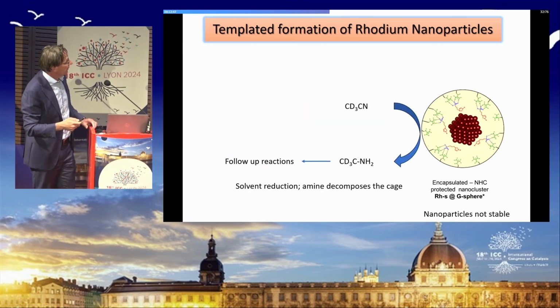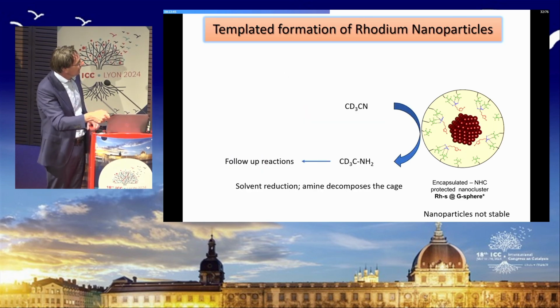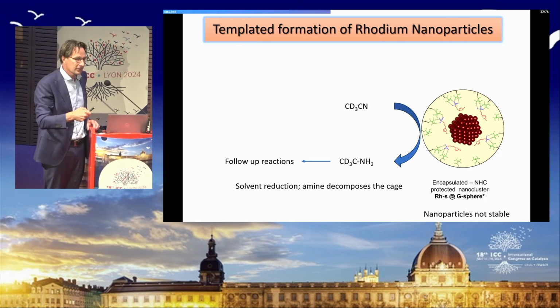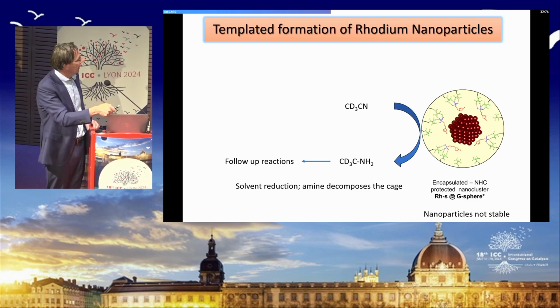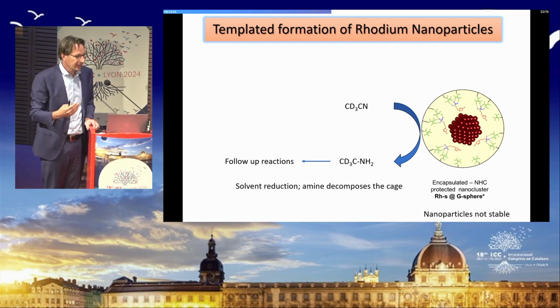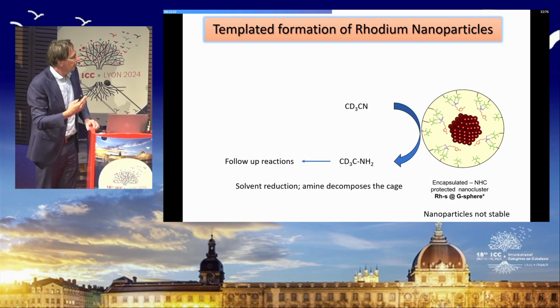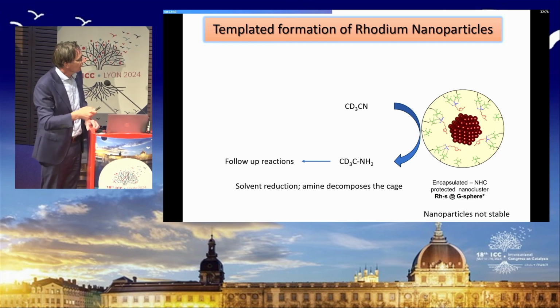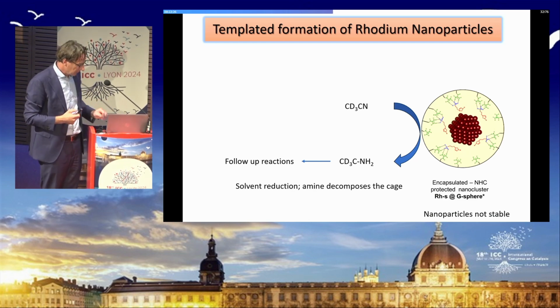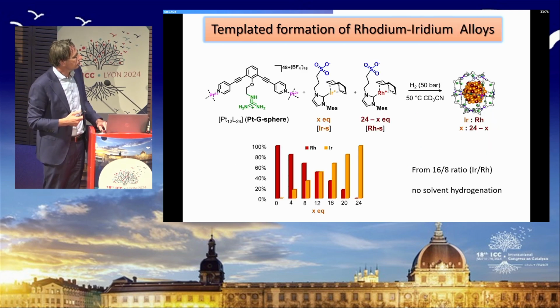So we thought about what was happening, and what we found is that these nanoparticles are so reactive that we also reduce acetonitrile as the solvent to make amines, primary amines, and follow-up reactions lead to secondary and tertiary amines. So we have byproduct formation. So yes, we can make the nanoparticle, but it is so reactive that we form byproducts.